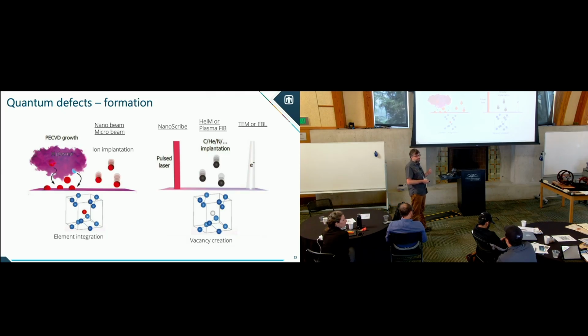And typically we want nitrogen vacancies close to the surface of the diamond, so they can be closest to the sample of interest. On this side, the CVD growth is usually only a few nanometers, so it's nanometers away from the surface. The ion implantation is usually low energy, so kilo-electron volts, so it's also only nanometers away from the surface. In some cases, we go up to microns if we want to do magnetic imaging, which is a lot of what I'll talk about. Then you can have a whole micron of NVs, but you don't want a 500 micron diamond full of NVs, because then your local resolution gets bad.